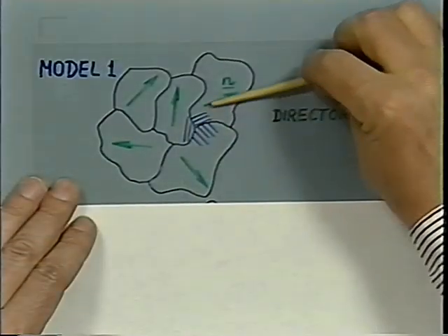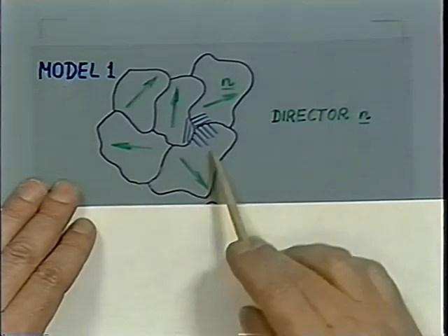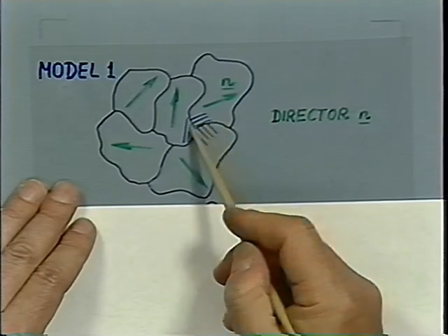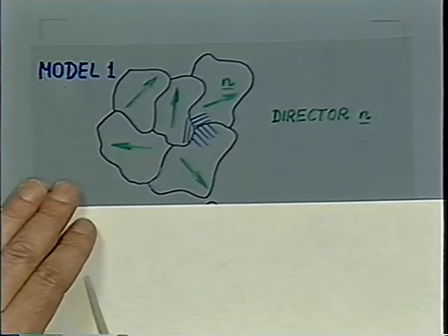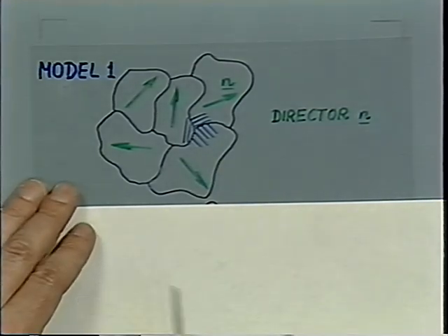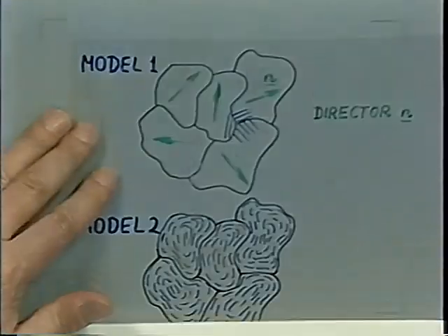On a larger scale, those molecules form some interesting morphology. Initially, one modeled the morphology as such, assuming that around a director vector, molecules are aligned like this in a domain which might be of micron size, and in a neighboring domain, the molecules might be aligned like this, and there's a discontinuity at the boundary. The picture of that model would be logs floating on a river and grouping up. However, I don't know of any liquid crystal which behaves like this.